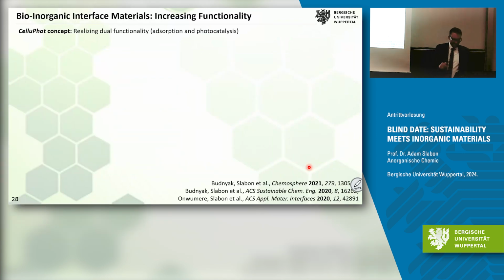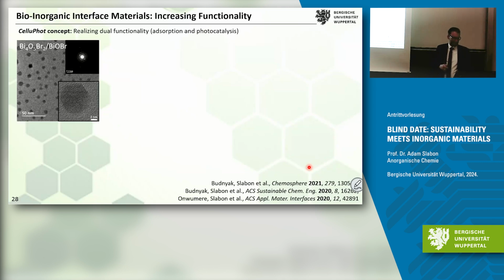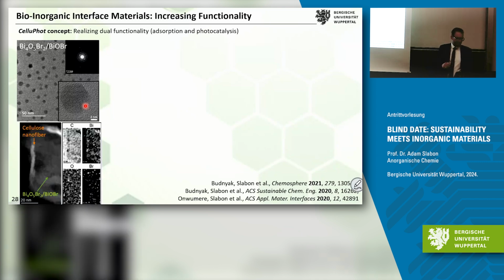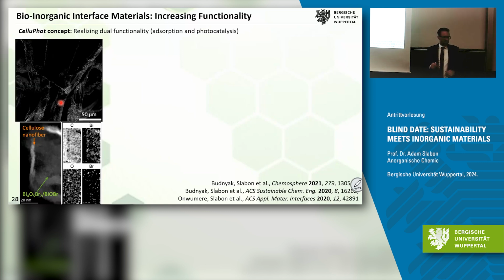So we made in the same year the CelluPhot concept. We grew hydrothermally at high pH on cellulose small semiconductor nanosheets of the bismuth oxygen bromide system. They agglomerate on fibers of cellulose, and we can scale this up to this size to get a membrane. You can see the SEM image here - this is cellulose coated with the particles, and it can do two tricks at one time.